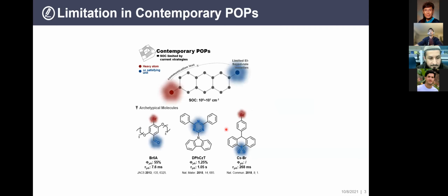So our contemporary POPs that people have designed these years, for instance, they usually have this certain kind of structure. For instance, we usually use bromine to induce heavy atom effect. And we do need another agent to satisfy the so-called angular momentum difference, which I will introduce later. And you can also fully remove the heavy atom, and they tend to give a lot longer lifetime, in the second to hundreds of millisecond regime.